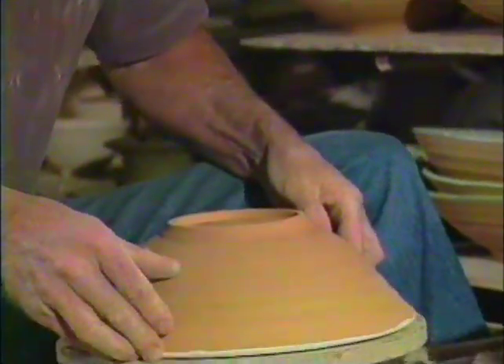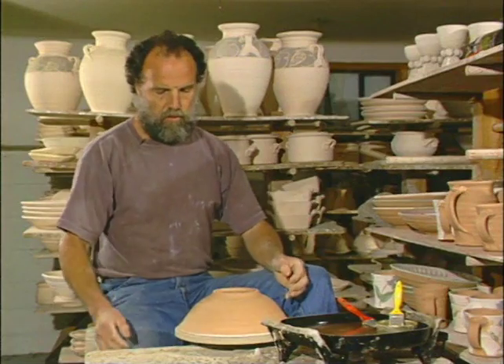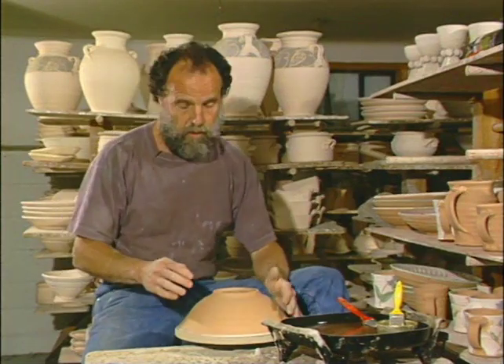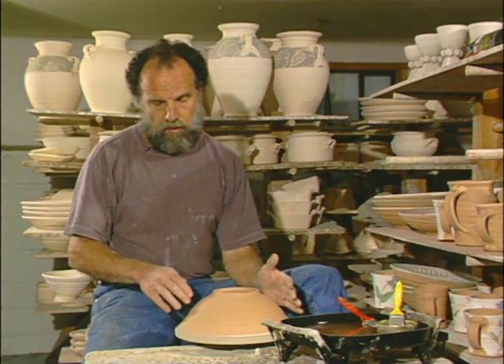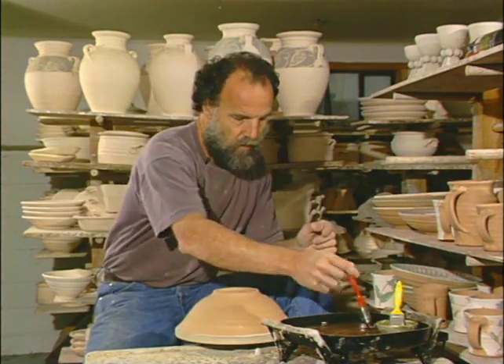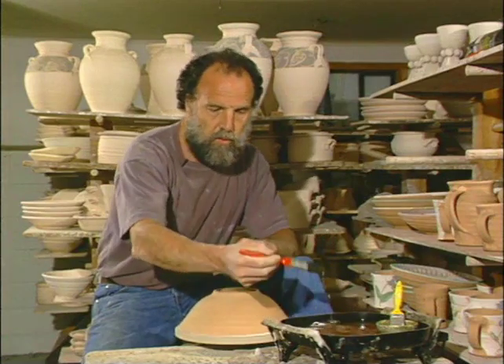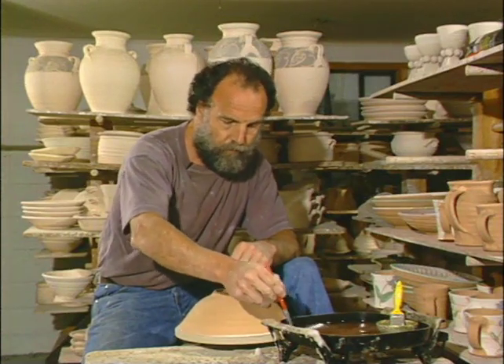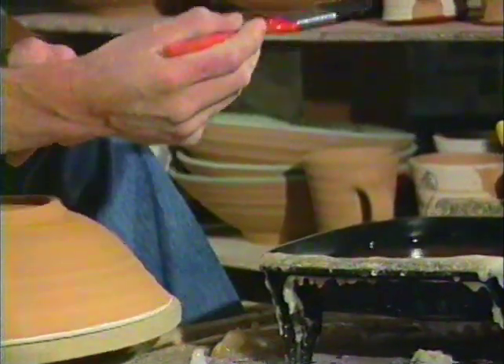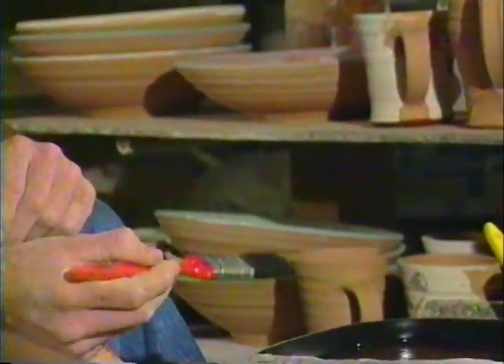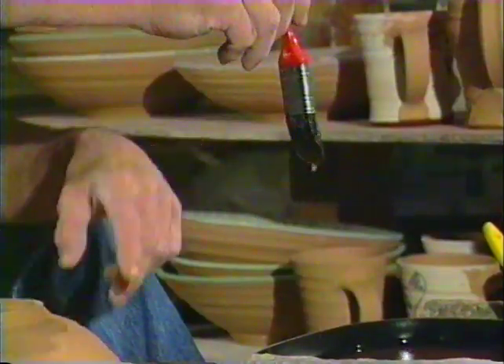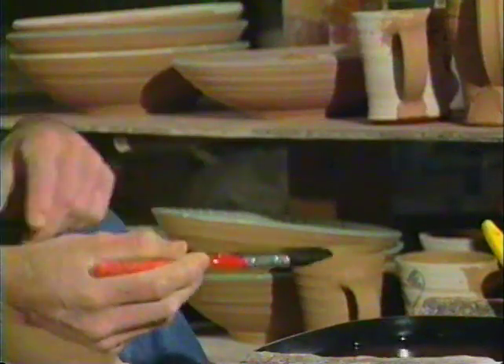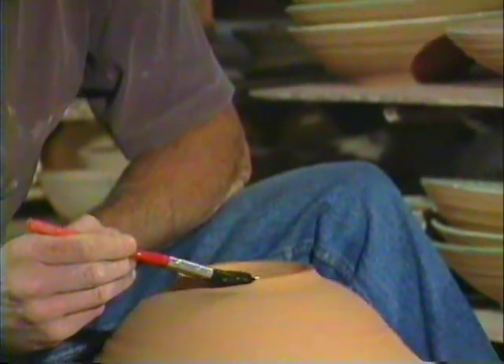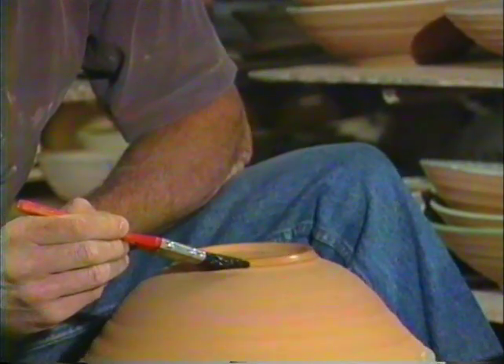Now, we can also apply wax to the bottom by using a brush on the wheel. First of all, we set it up, or on a banding wheel for that matter. That's quite satisfactory too, but as before when I was decorating, a kick wheel is certainly an easy controllable tool. Okay, so we've just got a regular bristle paintbrush here, and as you take it out of the wax, make sure that you carry the brush horizontally. If you take the wax out of the brush and turn it upside down, wax will dribble straight out of it. So you've got to take the wax to the pot with a horizontal motion, apply it like so, quite deliberately, let it flow out of the brush, and then carry the brush away horizontally.